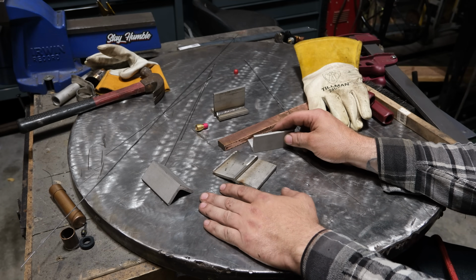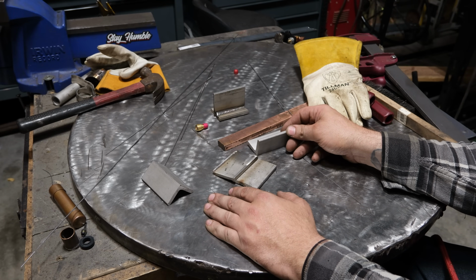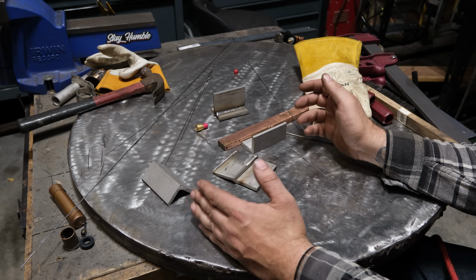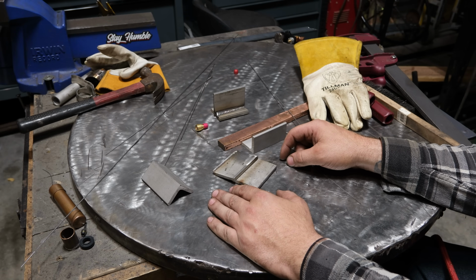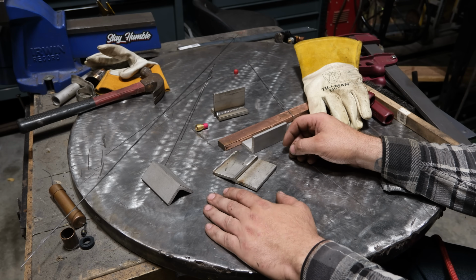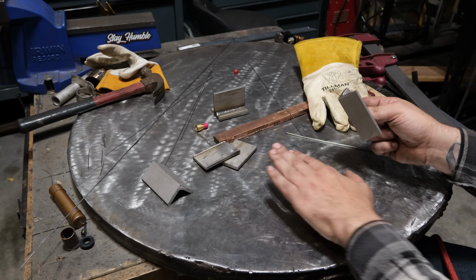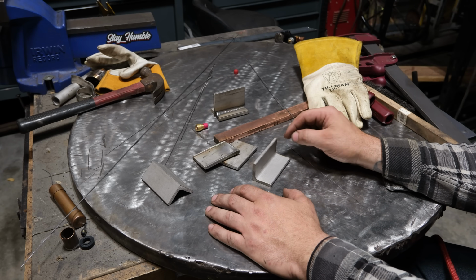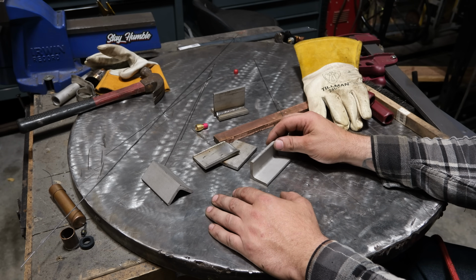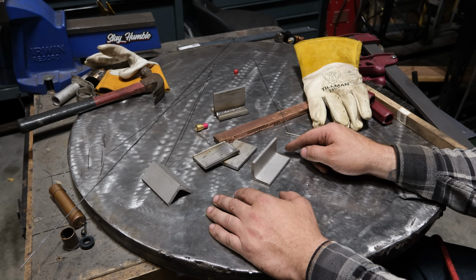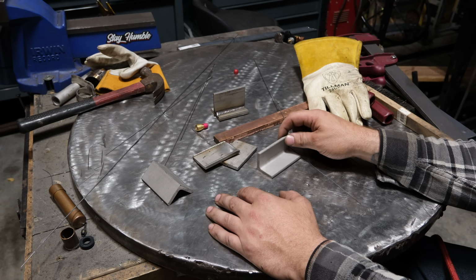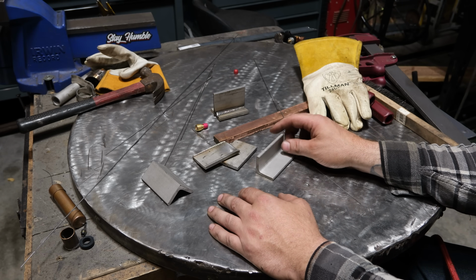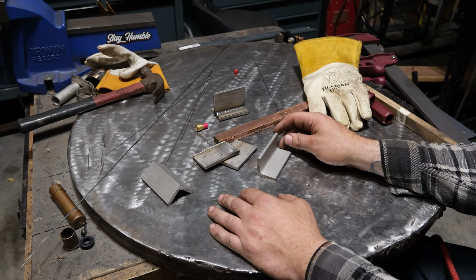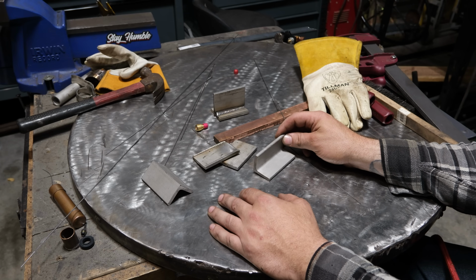Another very important aspect of stainless is, as you recall, I mentioned that it's a poor thermal conductor in comparison to steel. Well, it also conducts electricity in a lot different way, in my experience, than steel. And it's very common, say you're welding on this bench here, to have a piece of stainless and you're welding it, and all of a sudden it starts getting the high-speed wobbles where it's rattling and shaking. I even had that happen to me earlier, and I ended up having to put extra weight on it to get it to ground.